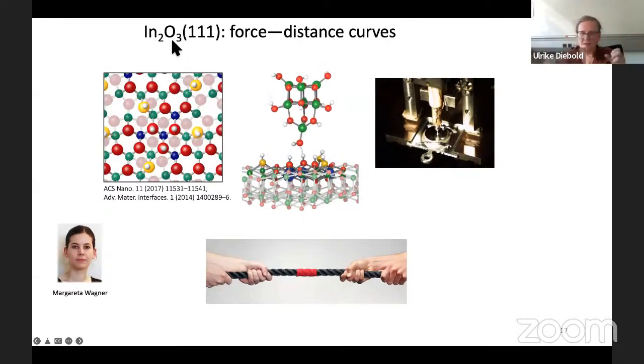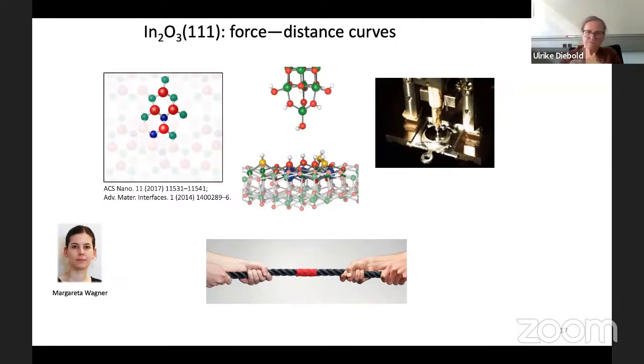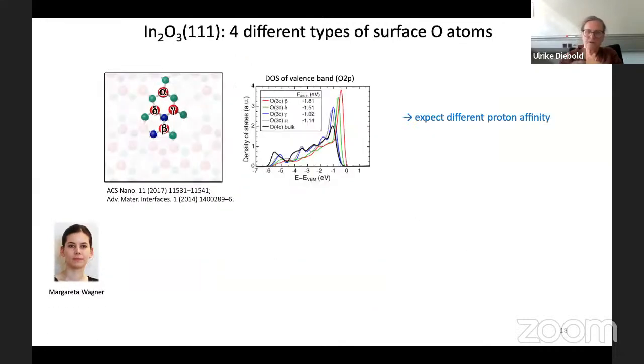That's a very big unit cell. And then just from the bulk structure, the bond lengths of each of these oxygen atoms, even if it's perfectly crystalline, the bond length and bond angle is just from the bulk crystal structure a little bit different, right? If you have a different bond angle and bond length, then the local density of states, or the local orbitals, if you want, of these oxygen atoms is a little bit different. So that's when it's perfectly crystalline.